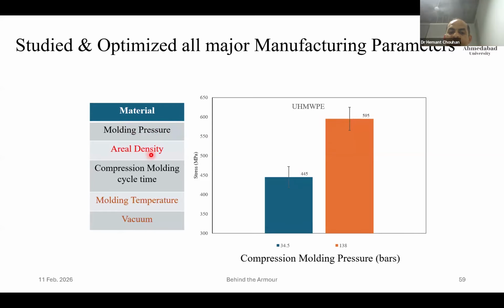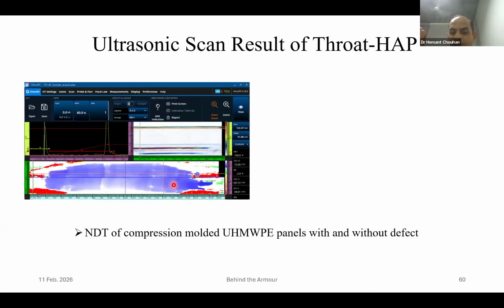Then we have the number of layers, the time, and the molding temperature. With a given machine, we can have a variety of ways to deal with the material system, so we can play with the properties of the same material. And then this is quasi-static data. Again, in high strain rates they will vary.